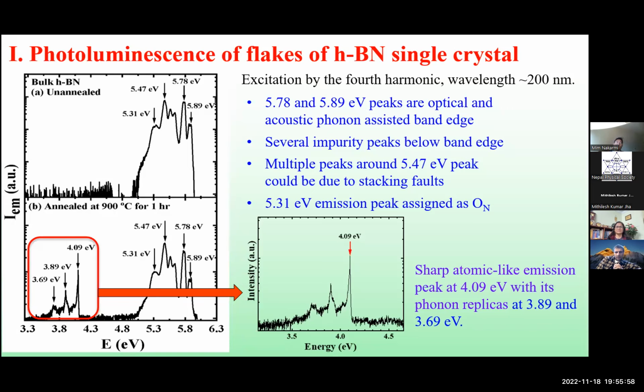There are also other peaks: 5.47 seems to be related to stacking fault, and 5.31 we assign to oxygen in nitrogen, but this is still in debate, and we are exploring more. In the bottom one, in the higher range, the emissions are similar, just with slightly different intensities. Below 5 eV, there is a feature which is not in the first sample.